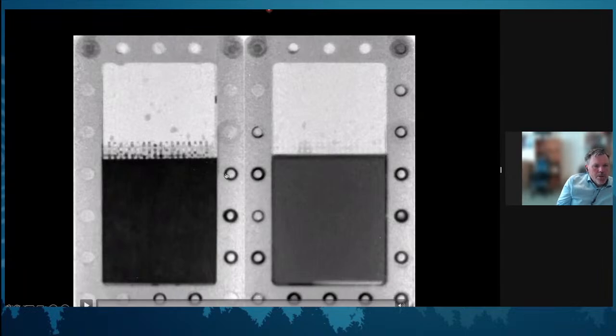When we start the experiment, we can also see that there are black rings here, and that is in the holes where we have the bolts. There is water agglomerated when we just have rinsed the system. So the first thing that we'll see when we heat it up is that this water boils away. And now we're going to see two different measurements made at two different times, but with the same time resolution. There is 2 seconds between each image.